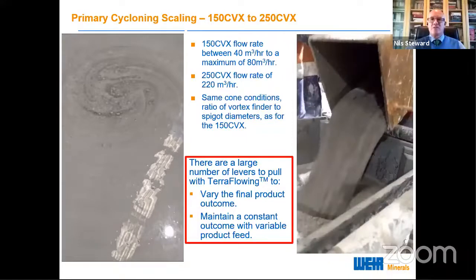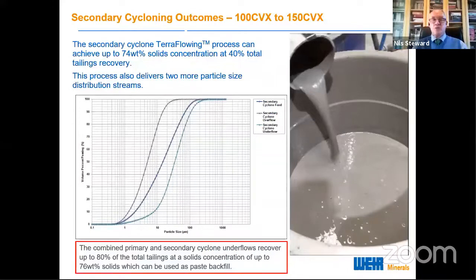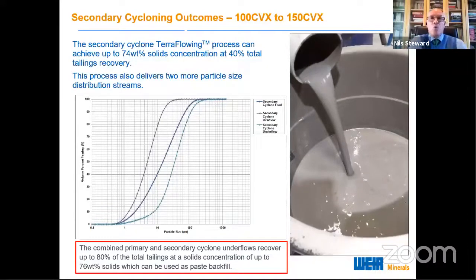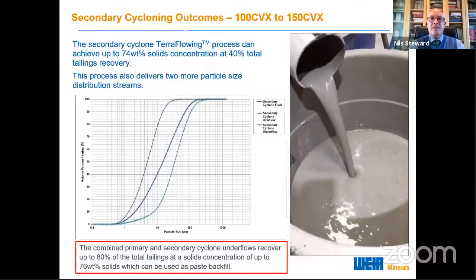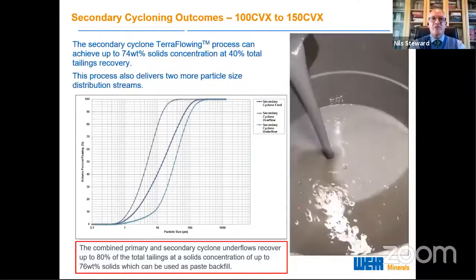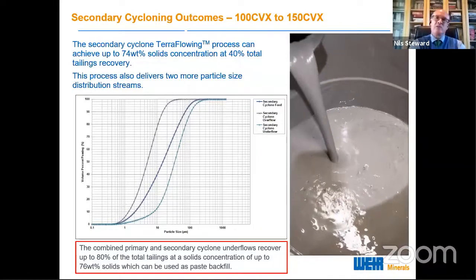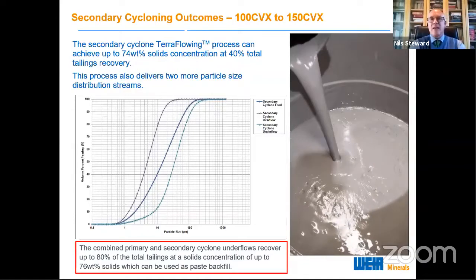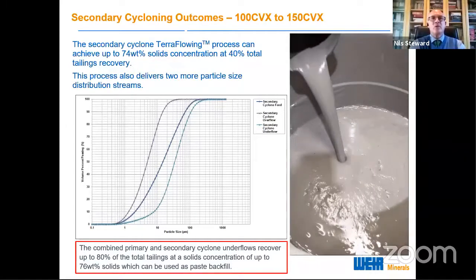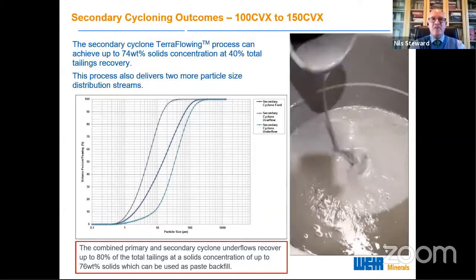So if we go to the primary cyclone overflow, we obviously now have a dilute product, and we need to thicken that and recover those tailings. The first work we started with was with a 100 Cavex cyclone, and this gives you an idea of the underflow solids concentration. Again, owing to the method that we operate the cyclone and what we inject into the cyclone, we were able to achieve up to 74 weight% solids concentration at 40% of the tailings recovery.